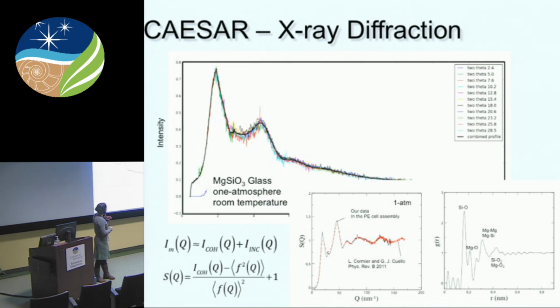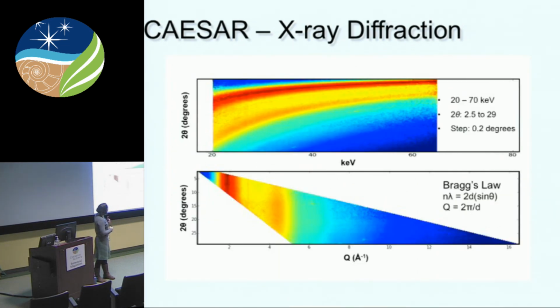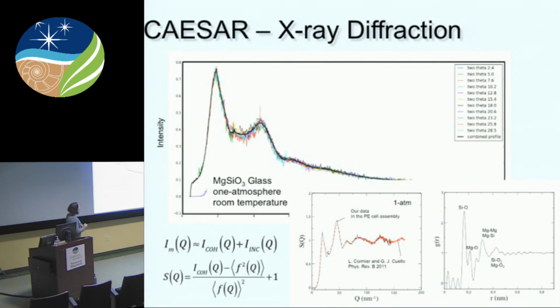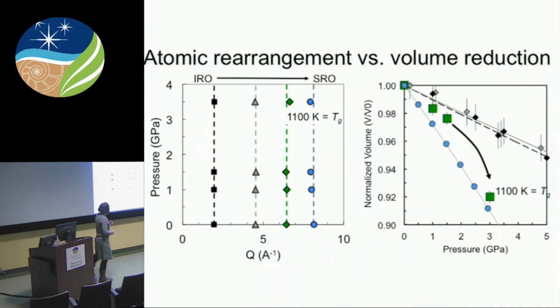Here is intensity for X-ray diffraction as a function of Q. We do CAESAR X-ray diffraction to pull out atomic structure information. CAESAR is just combined energy and angular dispersive X-ray diffraction. So we're collecting what would normally be a crystalline data set, but we do it as a function of energy and angle. Then using Bragg's law, we can convert that to Q as a function of angle. We can stack these, normalize them a bunch of different ways, and we end up with this curve. From intensity as a function of Q, we can calculate the S of Q, and then the G of R, the pair distribution function. The important thing is that from this data, these peaks correspond to atomic spacing. So this is what I worked on.